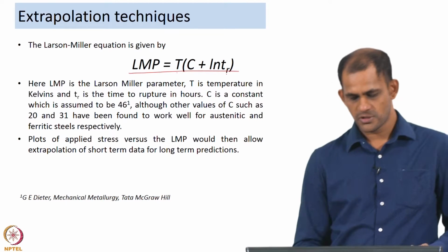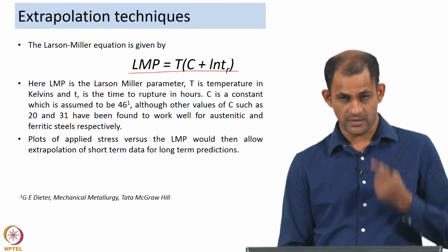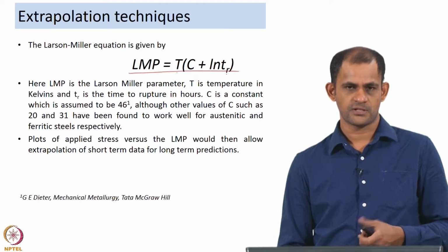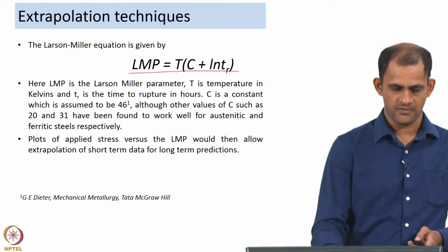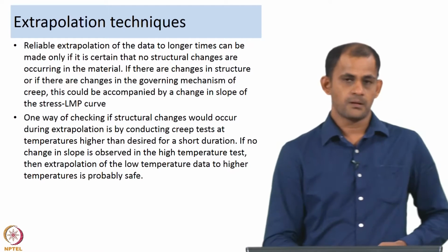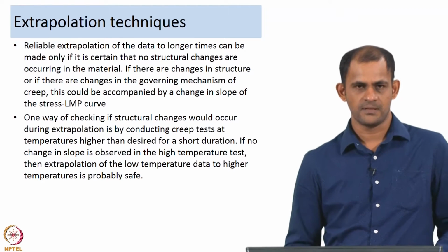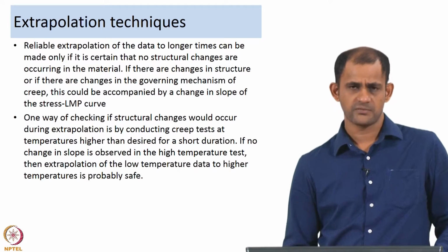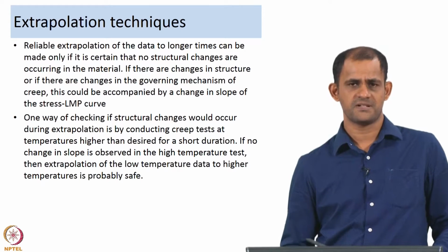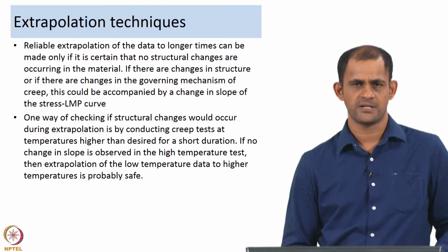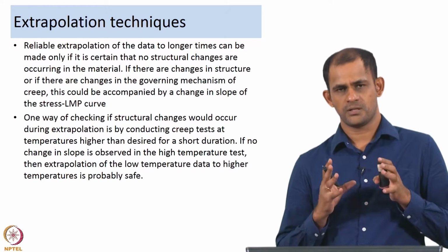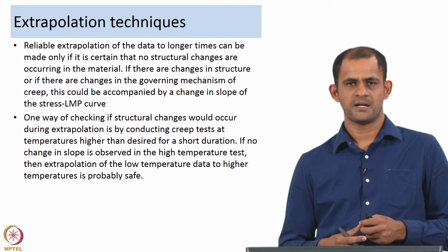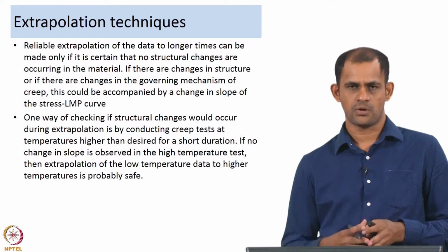Now, the approach, like I mentioned, is to make a plot of applied stress versus the Larsen-Miller parameter, and use it for carrying out extrapolation of short term data to long term performance. Of course, such extrapolation is reliable only if it is certain that no structural changes are occurring in the material. When you are doing a short term test and using it for long term performance, you have to be sure that the material behavior has not changed over the longer times.